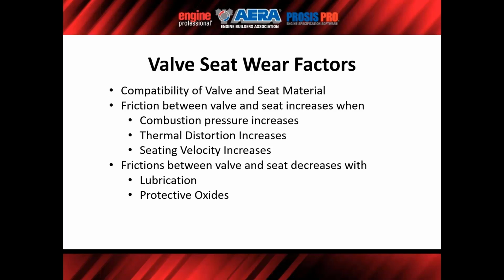Some of the other factors are friction between the valve and the seat. That friction increases with combustion pressure increase, thermal distortion increase, and as seating velocity increases. In the performance world, we typically want to accelerate that to eliminate some of the scavenging effects from one to the other. So we try to move the valve back to the seat very quickly, and for the duty cycle. And then friction between the valve and the seat decreases with